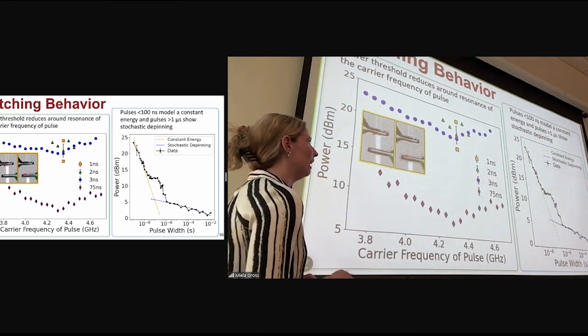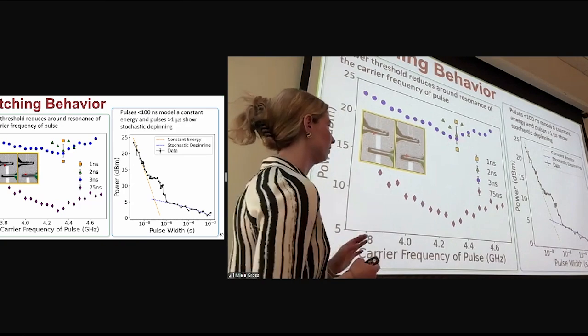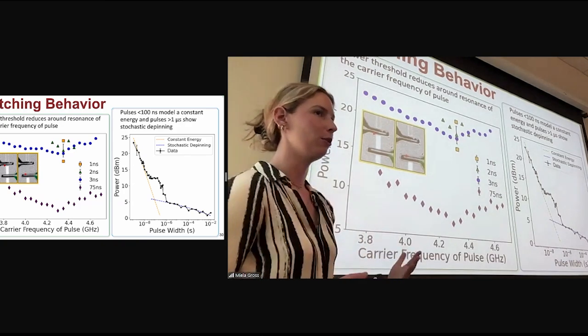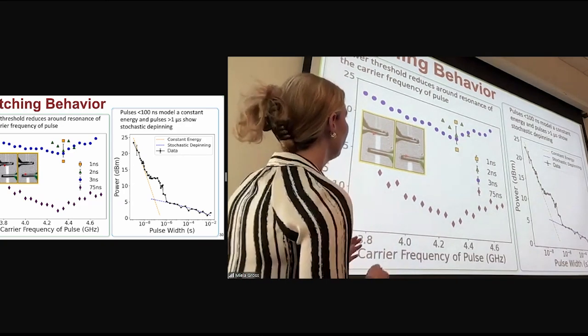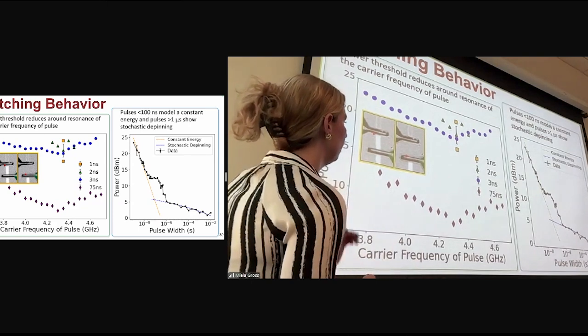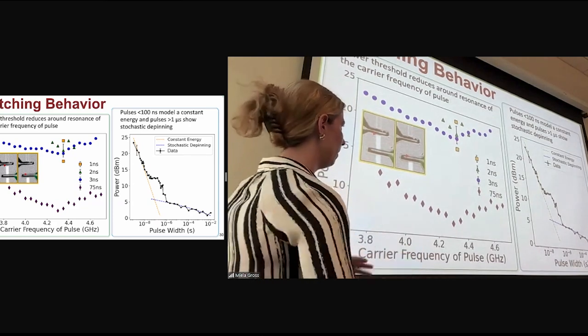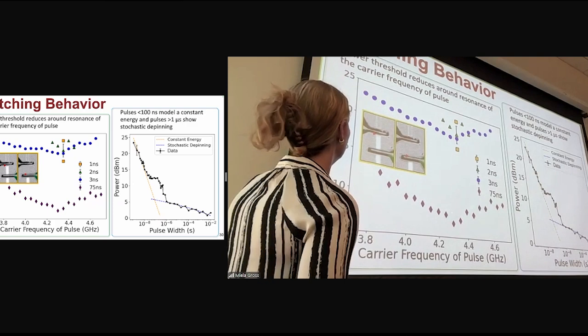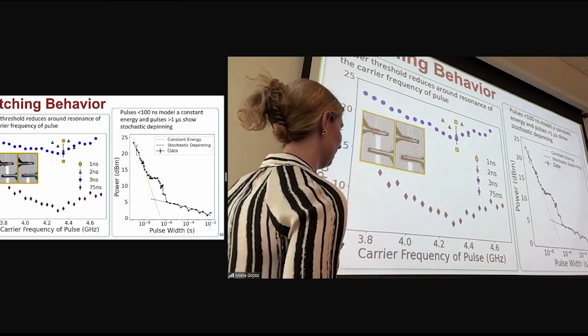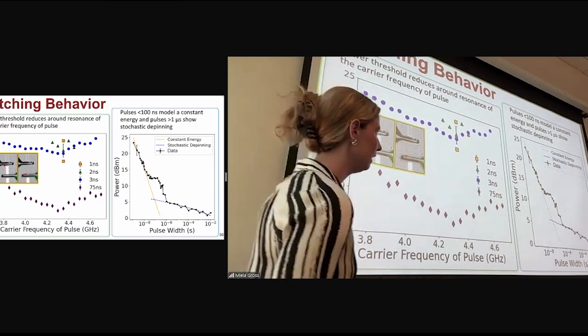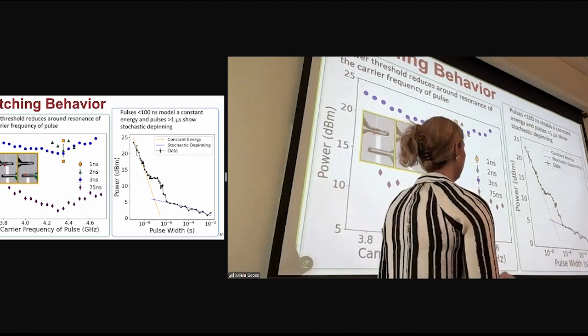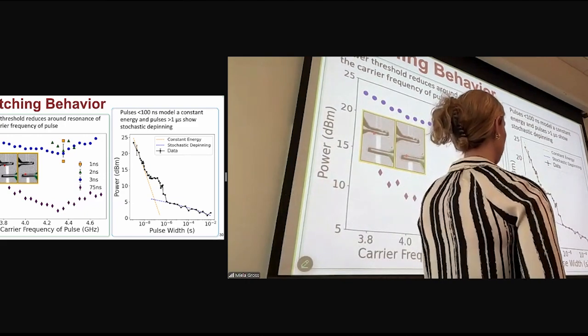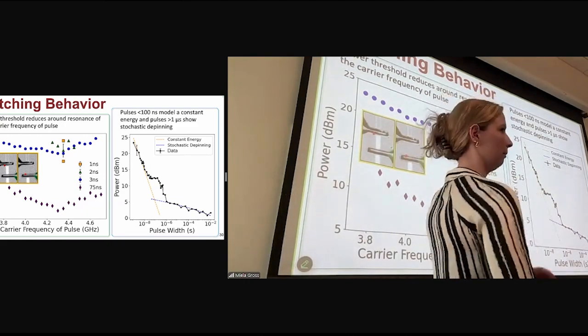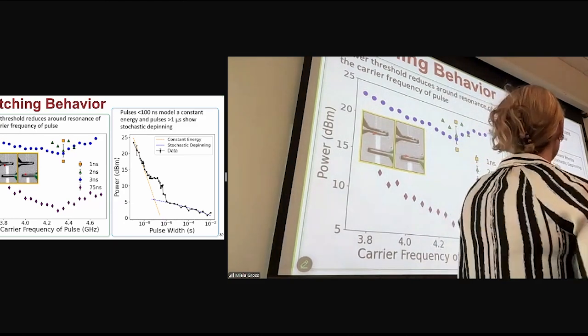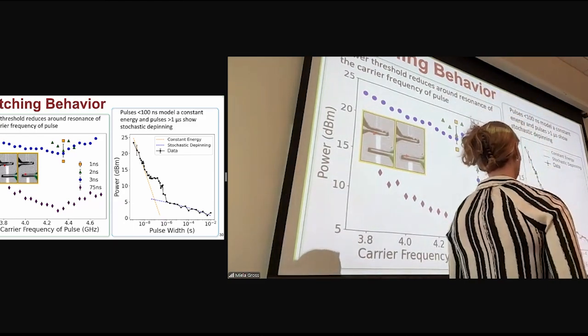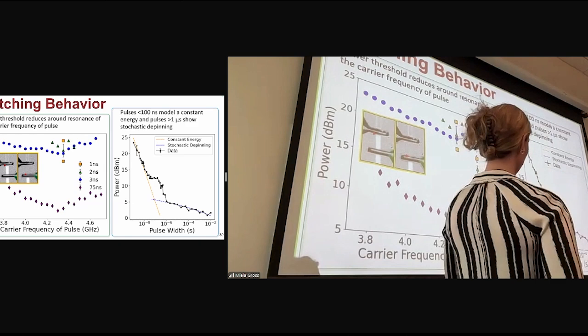As our pulse width widens, we see the range of carrier frequencies that can induce domain wall motion also increase. However, there's always still a dip, or minima, around the resonance of our device. If we move to the right here, we see increasing pulse width decreases the power threshold needed to move the domain wall. However, there are two specific regimes that this trend is following.